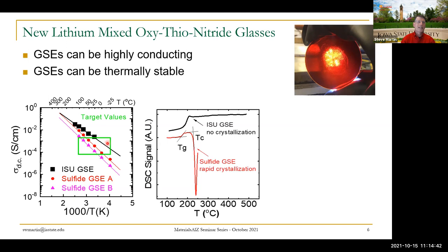But another one is processability. I'll spend some time talking about how we make a very thin piece of glass. Because in our lithium ion batteries, that polymer membrane is 30 to 60 microns, depending upon the manufacturer. We need also to be in that range, 30 to 60 microns, so we can get the overall resistance down. In order to do that, you need to be able to form the glass. And so if the glass crystallizes in its working range, you can't do that forming. But if it doesn't crystallize like some of our compositions, then you can lower the viscosity, get it into the working range, and then draw films from them like I'm going to show you today.